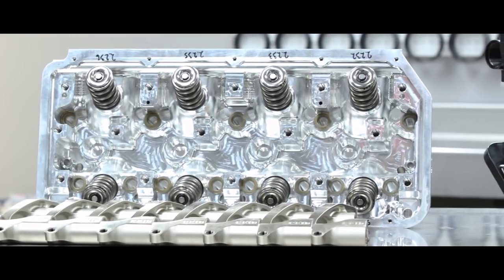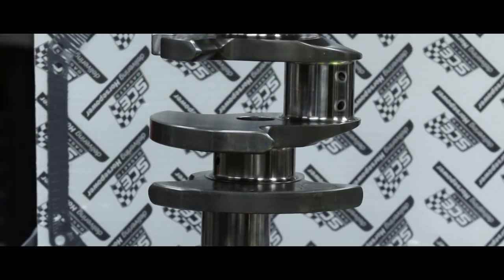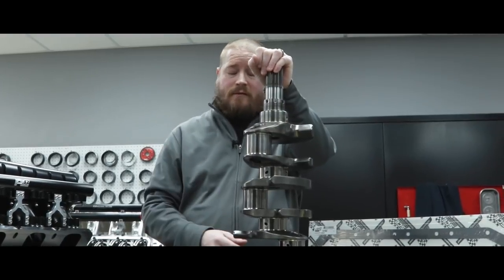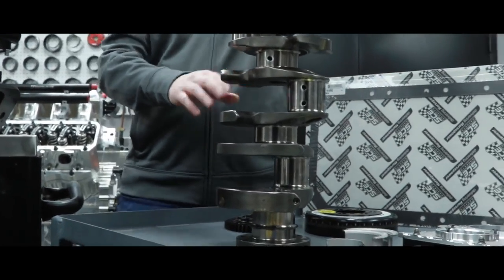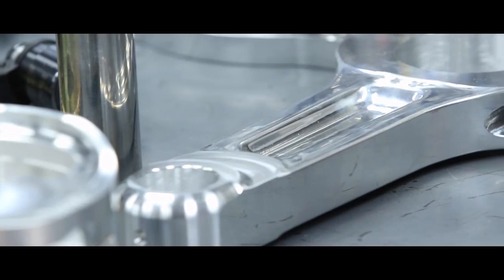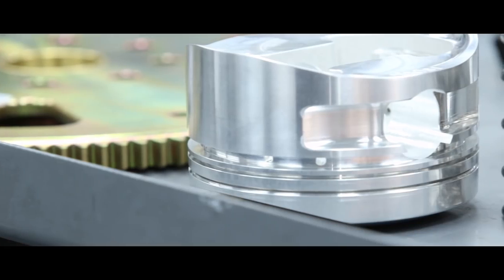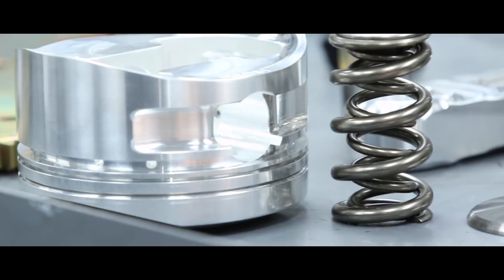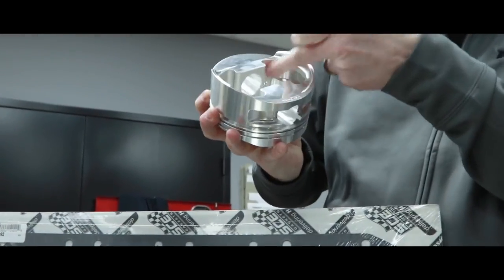We use a Bryant billet crankshaft with a larger wing design in the crank throws — it's a bit heavier duty where the throw meets the main, to add strength. We utilize an eight-counterweight design on all of our engines; these tend to flex a lot less under duress and high power. We use Clevite Vandervell-style bearings in almost all of our engines — 481s and Hemis especially. Our rods are Bill Miller rods, used almost exclusively. The piston is used in different compression ratios and dome heights across basically all of our Hemi engines, with a lot of reinforcement towards the bottom of the pin boss. It's a forging — you can see where the machining is done and where the rough areas are from the forging.